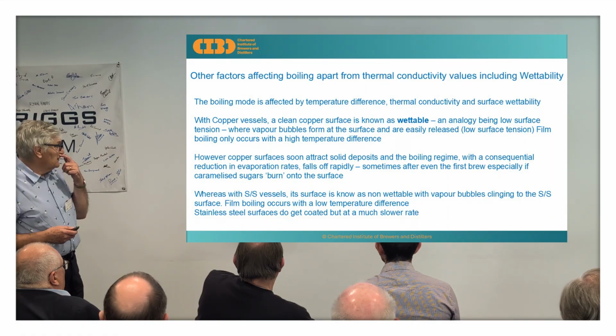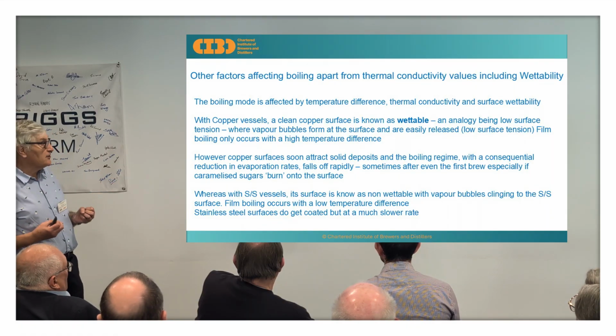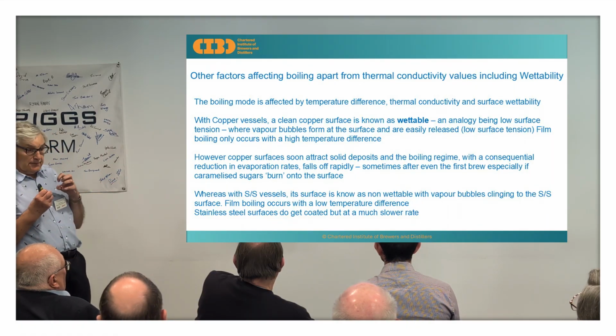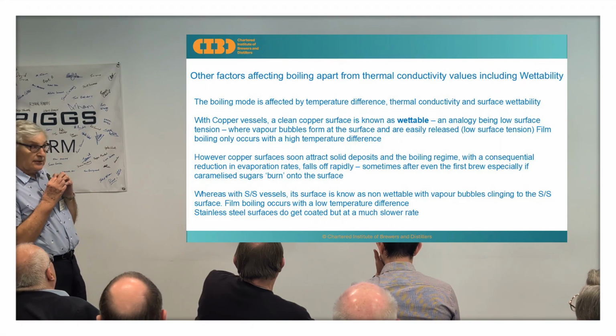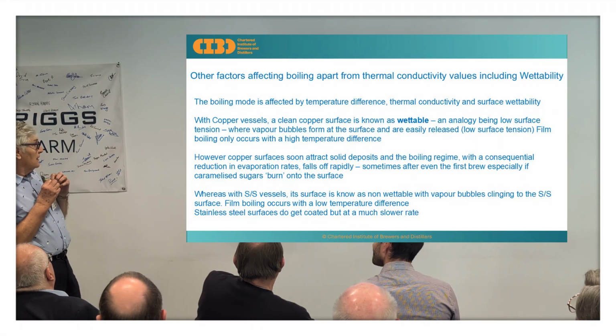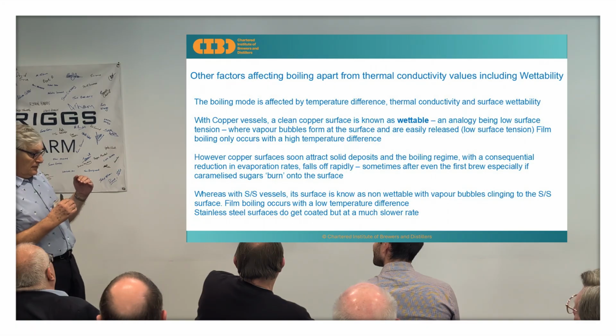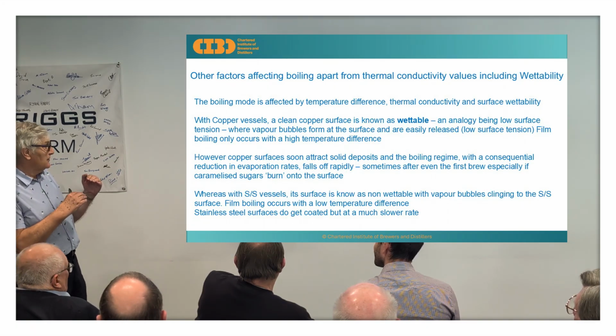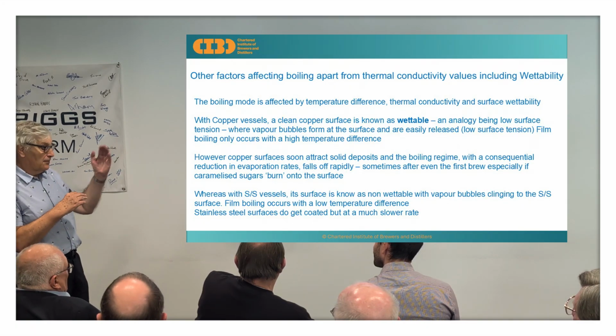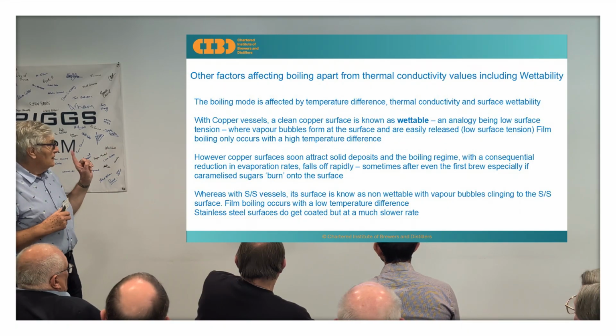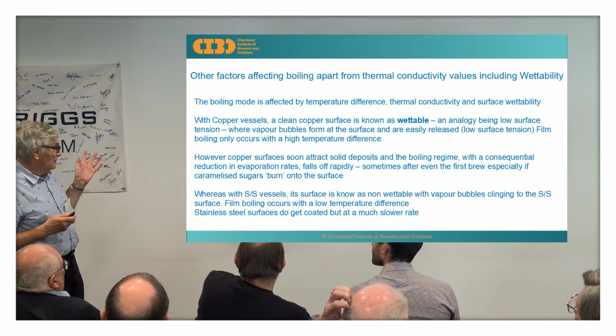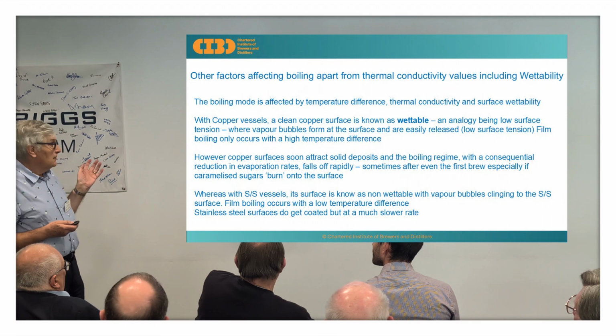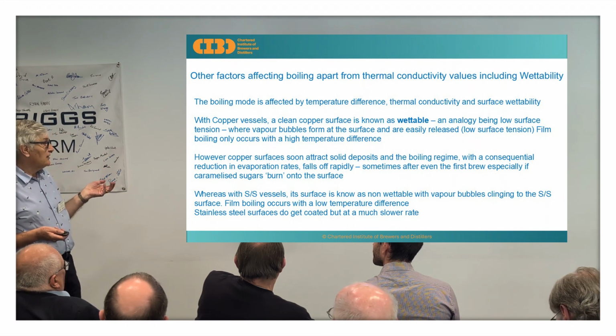Stainless steel, on the other hand, its surface is known as non-wettable. The vapor bubbles clinging to the surface saying, I don't want to leave, I don't want to leave. But here, this film boiling occurs at a lower temperature, and you do get the bubble eventually leaving. Stainless steel surfaces do get coated, but they get coated at a much slower rate.